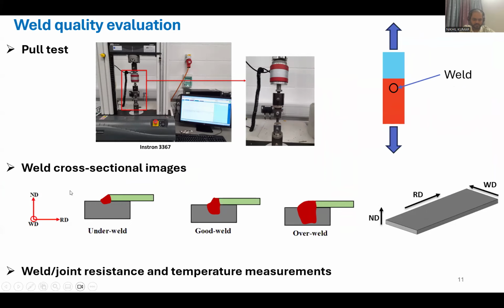And the second one is the weld cross-section analysis. As I mentioned, you have to capture the weld strength as well. You have to check whether this has 100% penetrated the bottom sheet or is partially penetrated. It should not be very low penetration.